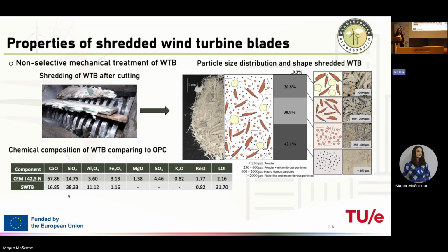You talked about the alkali environment that proceeds from the cement mixtures. How do you tackle the degradation that this alkali environment may have on the glass fibers? Yeah, so we use a standard method from the American Society for Testing and Materials for measuring the expansion after 14 days of testing.